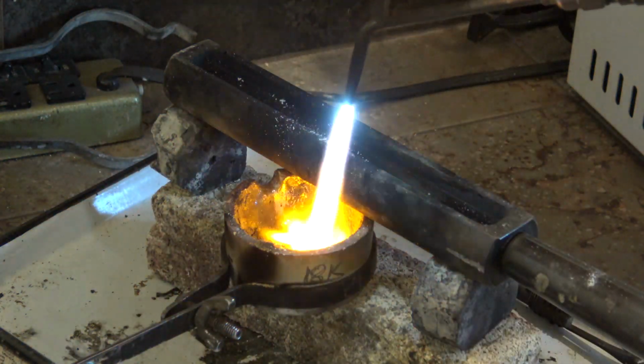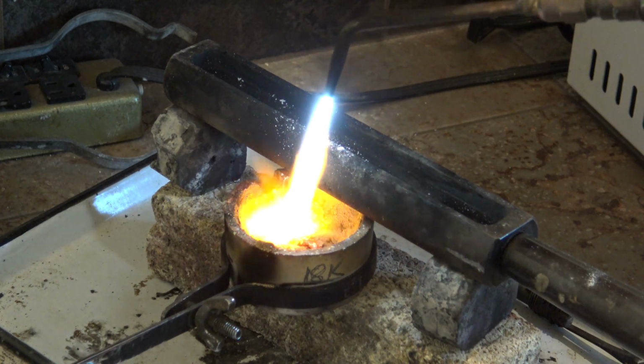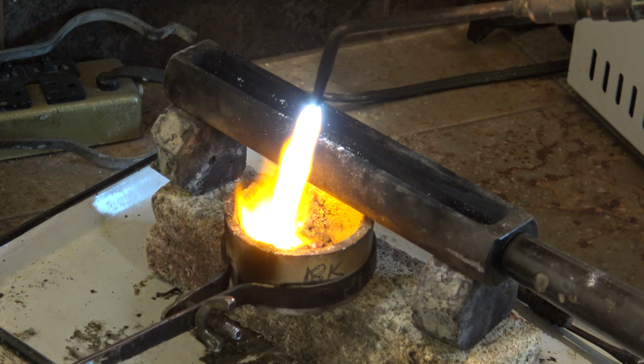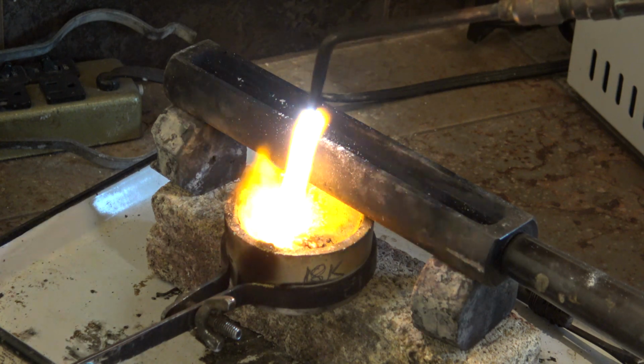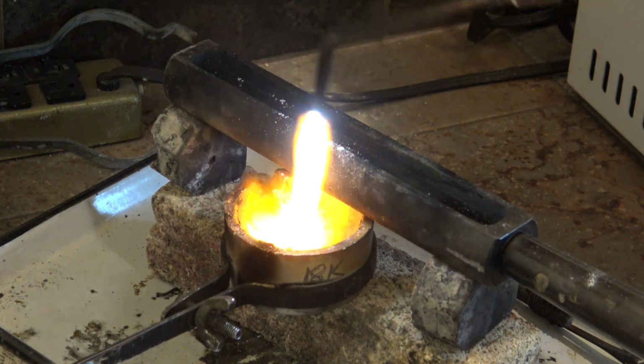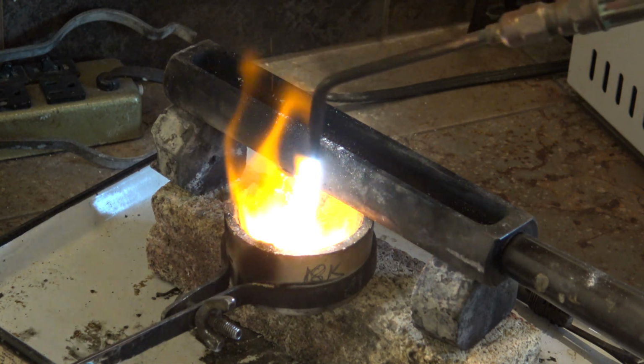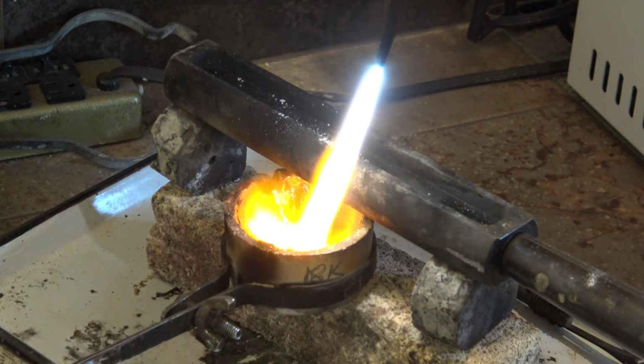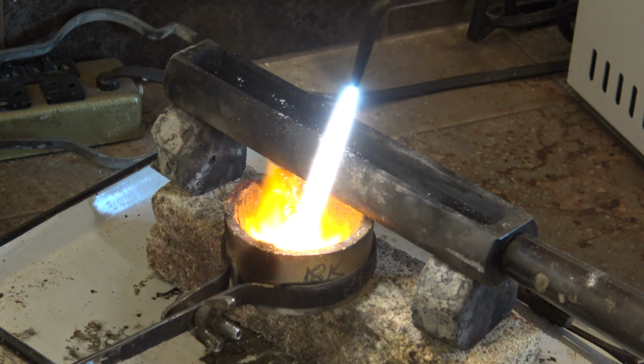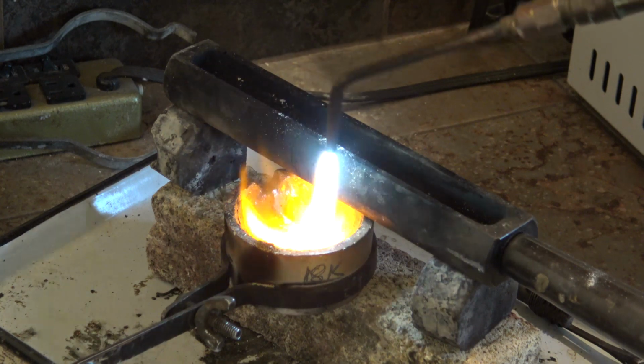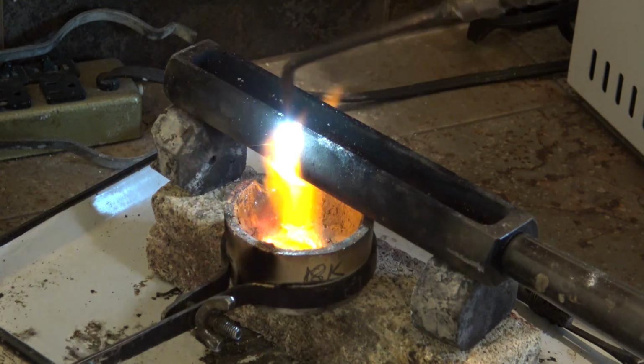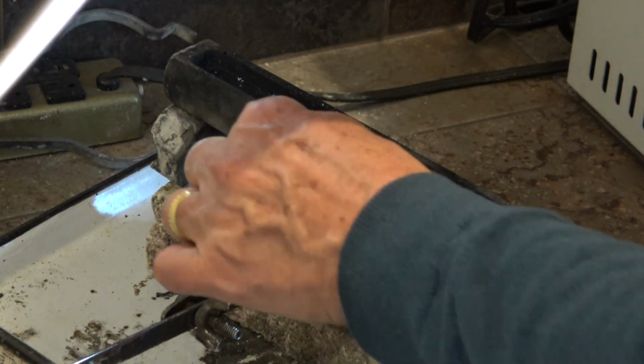So this process goes on for a while. I do this very gradually because you don't want to overheat any one section. You want to very gradually let the borax soak into the filings so it can remove all the impurities from between the filings as they're melting together. When you do it this way, the filings will melt into a beautiful smooth ingot or puddle of gold.